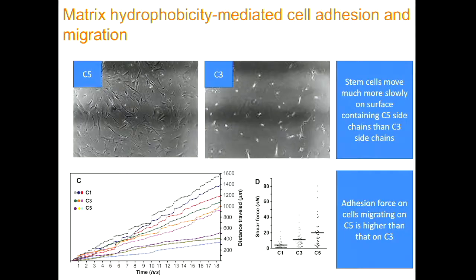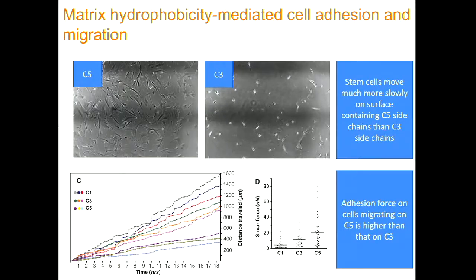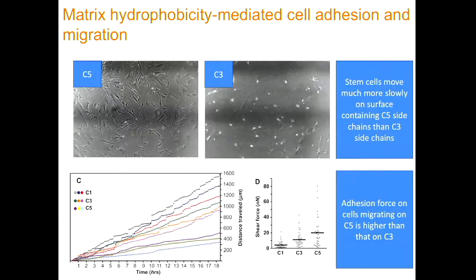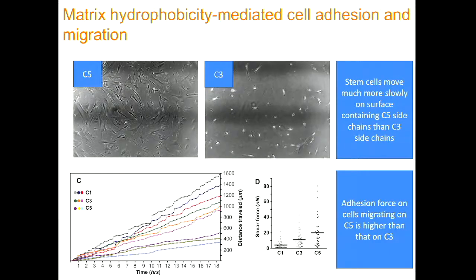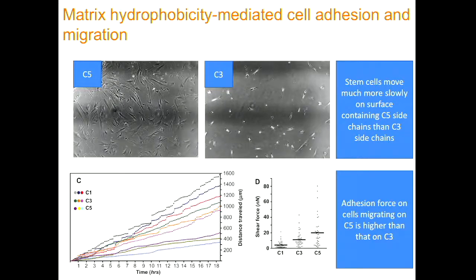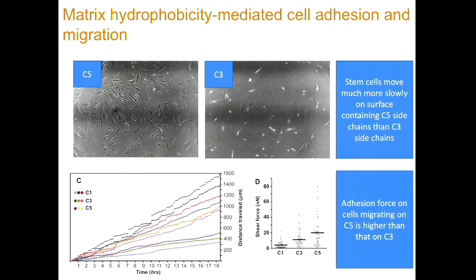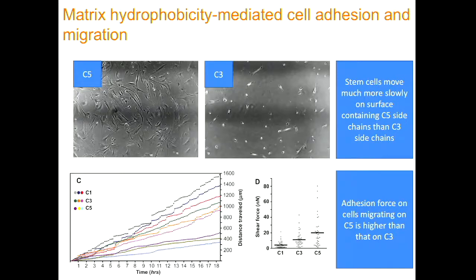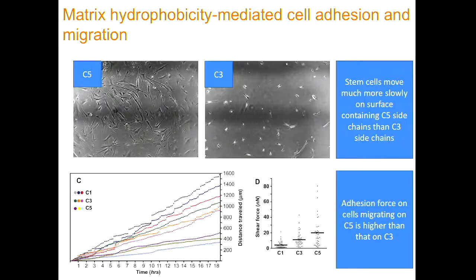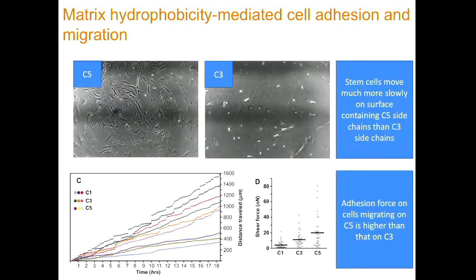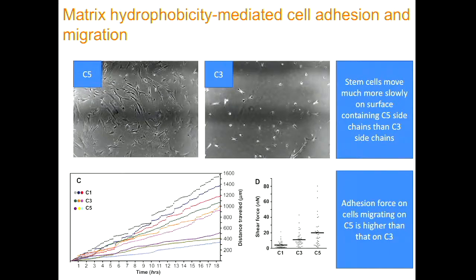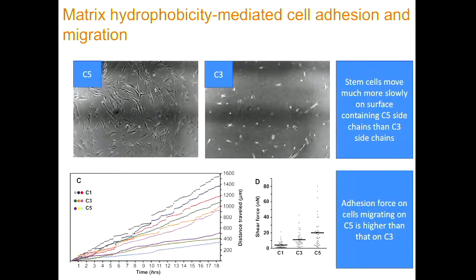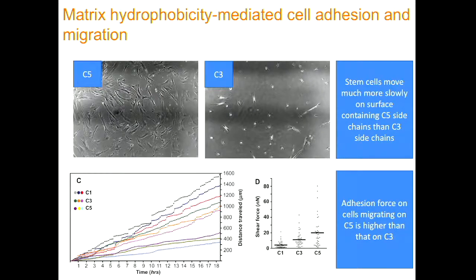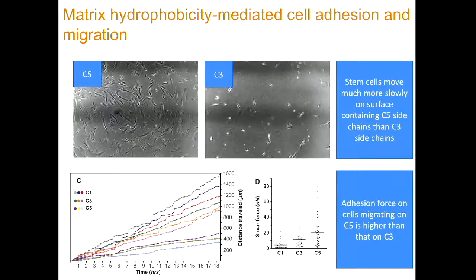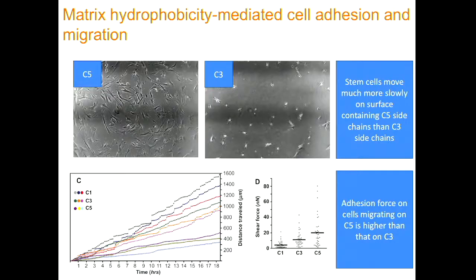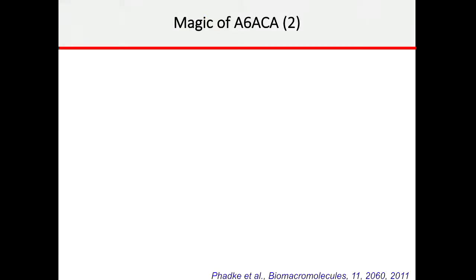If you see here, stem cells move much more slowly on surfaces containing the C5 side chain, that means acryloyl 6-aminocaproic acid, than the C3 side chains. And if you look at the adhesion force on cells migrating, C5 is actually the highest. We would have never imagined when we did acryloyl 6-aminocaproic acid as a result of our polymer science work that this will have some say in terms of this issue.